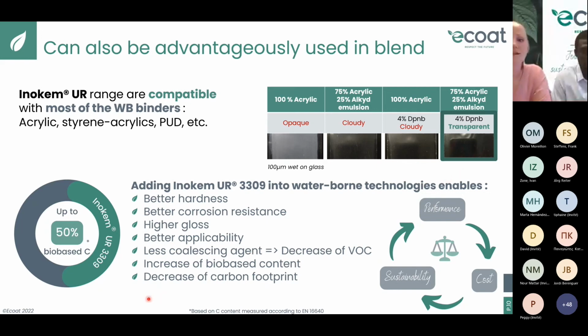And the last but not least, you can decrease carbon footprint. As I said earlier, the Inokem UR range can reach at least 50% of bio-based content. And in our case, this decreases carbon footprint of the product. In some cases, you can even divide by 2 or 3 the carbon footprint of the binder in the formulation. As a result, with the blend, you can reach a right balance between costs, performances, and sustainability.